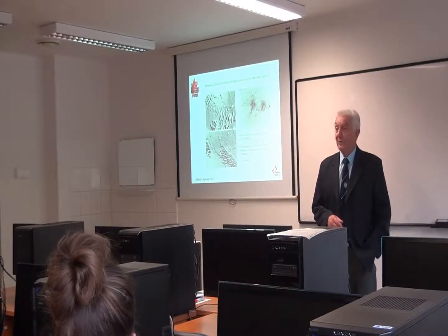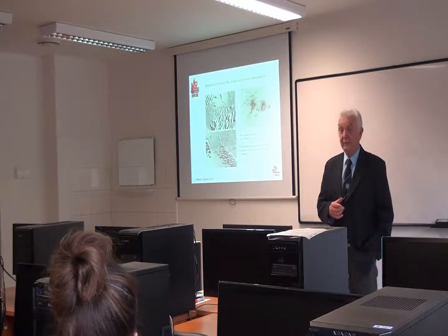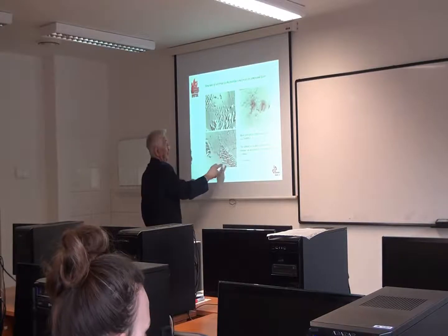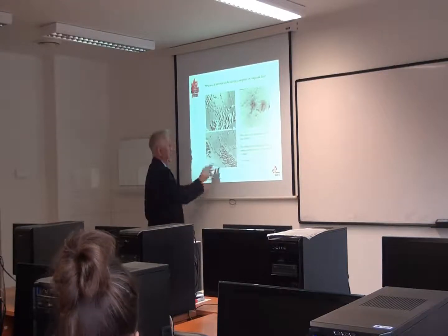Well, these are two important pictures because they were unique in the world. They were the first time that we demonstrated using electron microscopy that the compound layer is able to dissolve the carbides in pearlite. You see, this is a typical pearlite region, and you see how the compound layer is protruding on the grain boundaries, and it slowly will dissolve the carbides.